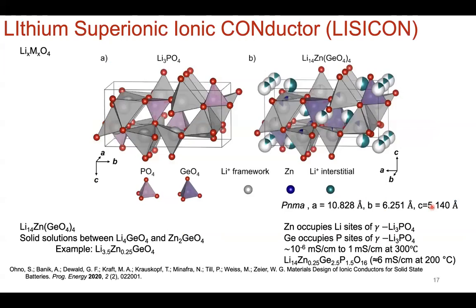So the garnet system has been heavily investigated and been around a long time. Of course, they're mostly air stable, which is a real advantage for processing and fabrication of electrochemical cells. But the search for higher ionic conductivity compounds has never really ceased, and it's an active area of research. In terms of other families of compounds that have high ionic conductivity, these lithium superionic conductors, or LISICON based materials, have also been heavily studied. And I keep saying high ionic conductivity as opposed to superionic conductivity, because it is generally accepted that superionic conductivity denotes that a material has an intrinsic ion conductivity of greater than 10 millisiemens per centimeter at room temperature.